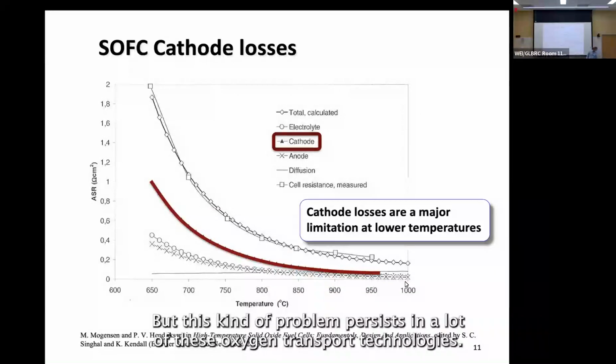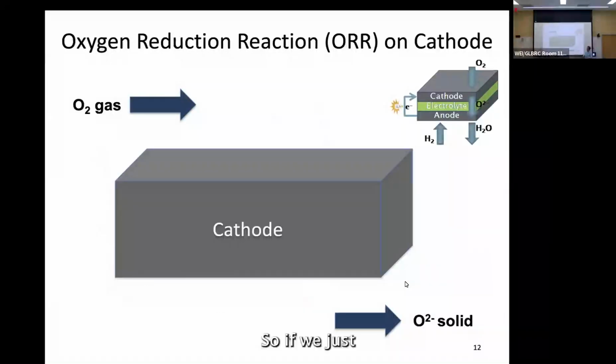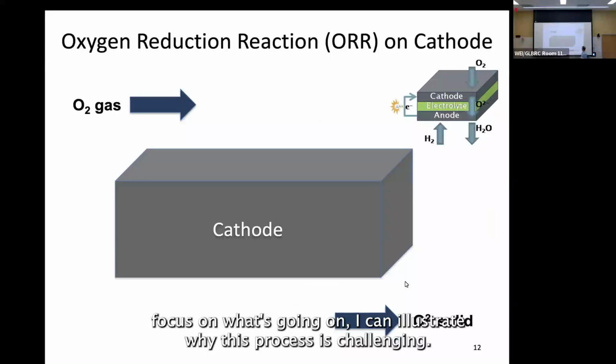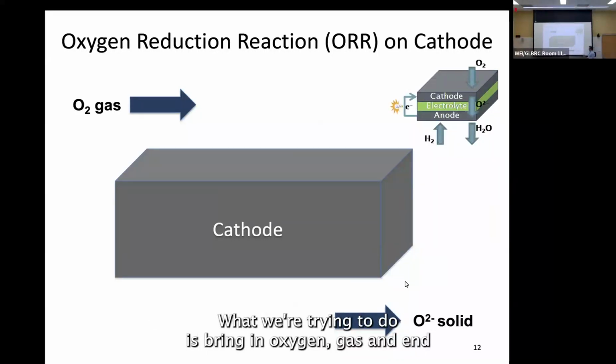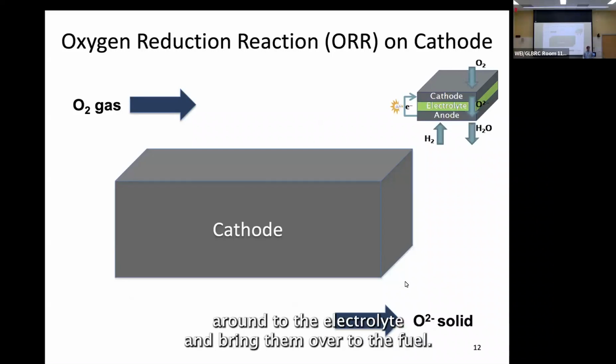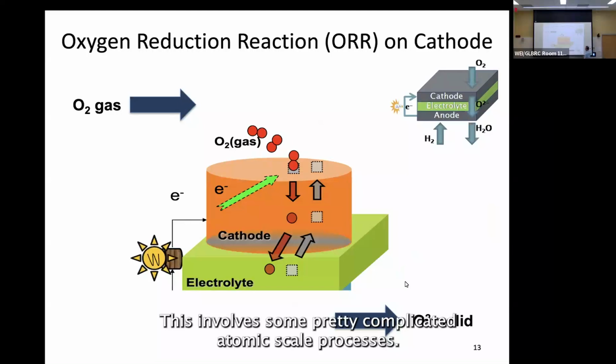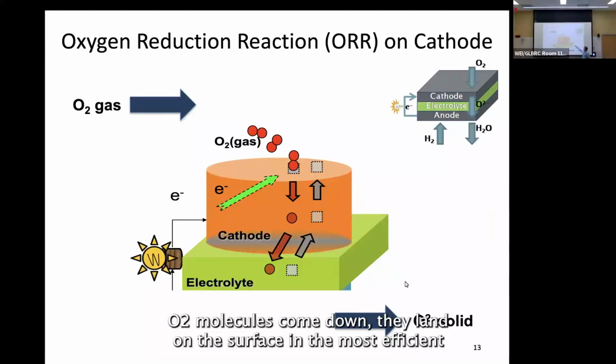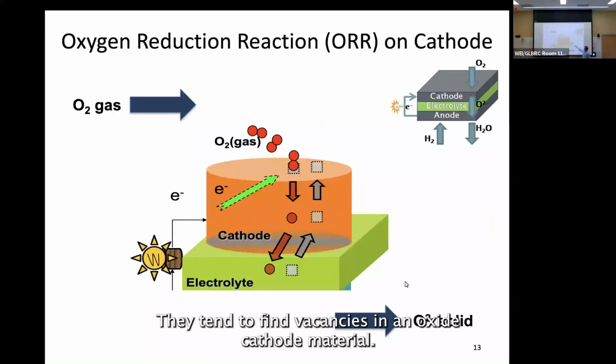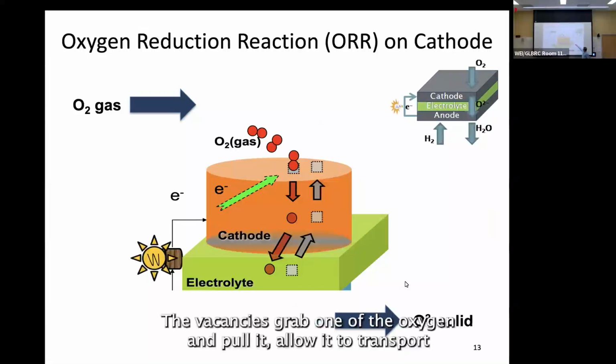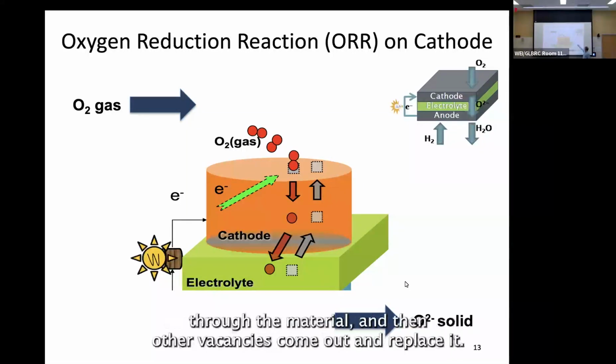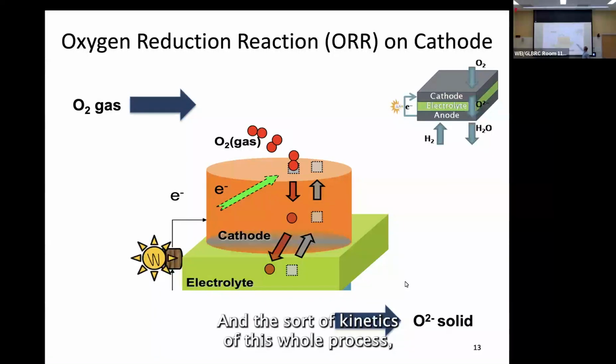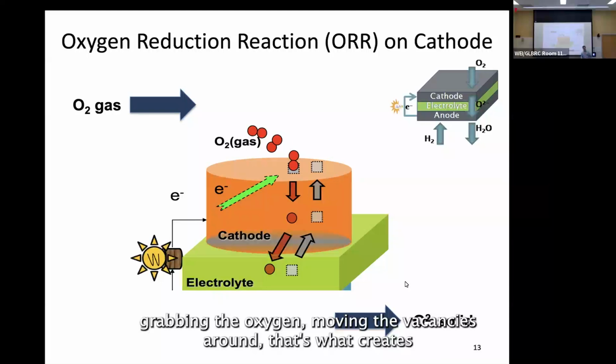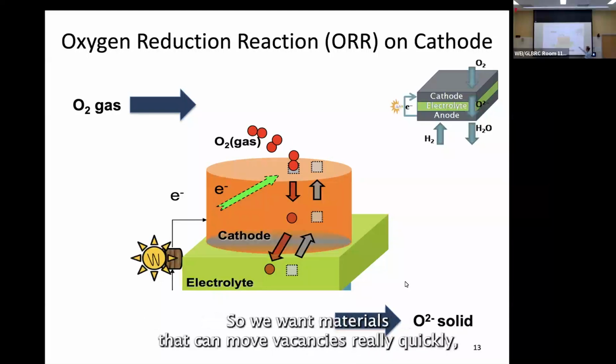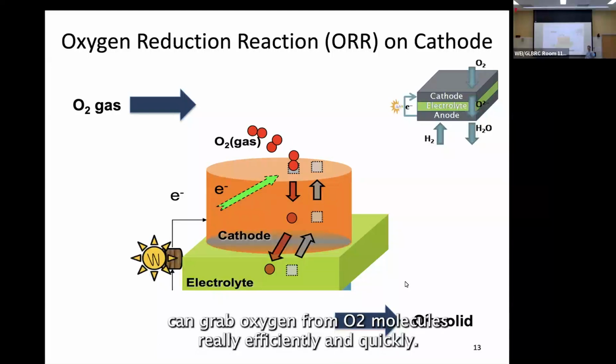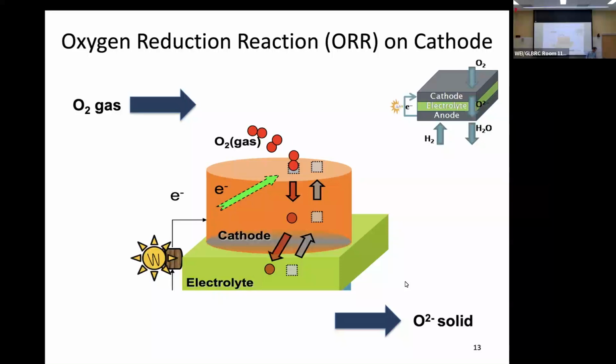But this kind of problem persists in a lot of these oxygen transport technologies. So if we just focus on what's going on, I can sort of illustrate why this process is challenging. What we're trying to do is bring in oxygen gas and end with oxygen ions in a solid form so that we can move them around to the electrolyte and bring them over to the fuel. This involves some pretty complicated atomic scale processes. O2 molecules come down, they land on the surface. In the most efficient materials, they tend to find vacancies in an oxide cathode material. The vacancies grab one of the oxygen and allow it to transport through the material, and then other vacancies come out and replace it. And the kinetics of this whole process, grabbing the oxygen, moving the vacancies around, that's what creates all the resistance that gives you losses at lower temperatures. So we want materials that can move vacancies really quickly, can grab oxygen from O2 molecules really efficiently and quickly. That's sort of our design problem.